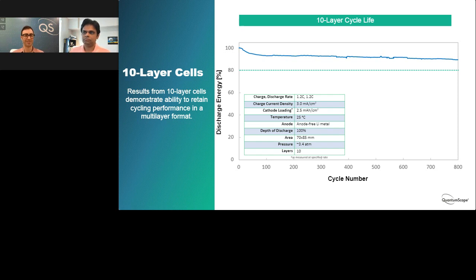And the last one of those was to show a 10-layer cell cycling under basically all the same conditions that we had a 1-layer cell cycling in. So over 800 cycles to over 80%. And on Tuesday, we announced that we had done that. This is the data from that cell showing that it's close to 90% after 800 cycles, as our 1-layer cells were. This was tested at a rate slightly north of 1C, actually 1.2C charge and discharge rates with average current